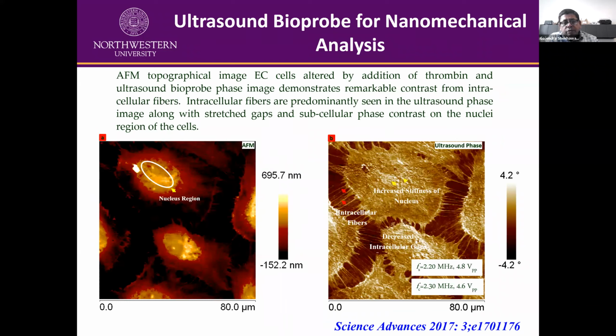And then this is another example, endothelial cells, and you can see that when we inject drug into these cells, stress fibers or intracellular fibers are formed. On the left, in the typical topography image, you cannot see them, but on the right side you can see pretty decent stress fibers that form and are reflected in the ultrasonic images. So wherever there is a change in mechanical properties, this ultrasound can pick up those mechanical variations and reflect them in the image.